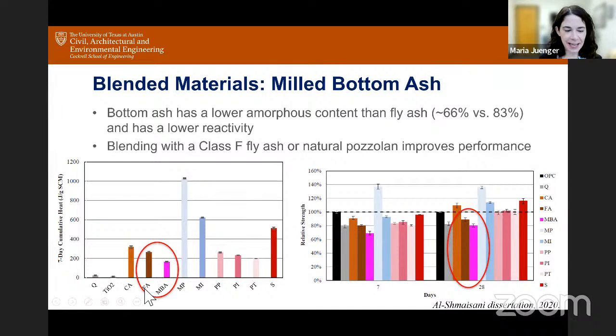Okay, so this is the fly ash, FA, that we've looked at before. This one that you were probably curious about before, the pink one, is MBA. That's a milled bottom ash. So this material is less reactive than a fly ash in this R3 test. It is actually on the borderline of what RILEM's recommendation is for a cutoff between being inert and reactive in this particular test method.